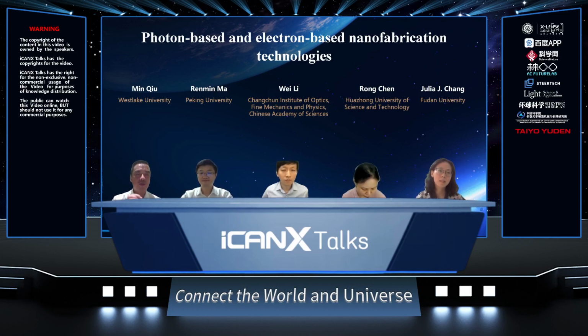It's actually tiny, small clusters of water molecules stacking with each other. In this amorphous phase, it's still solid, and the molecules interact with electrons easily. They will absorb electrons and become heated a little bit. And sometimes not only heated, but the hydrogen will dissociate from the water molecules and they will evaporate. So this is the process.